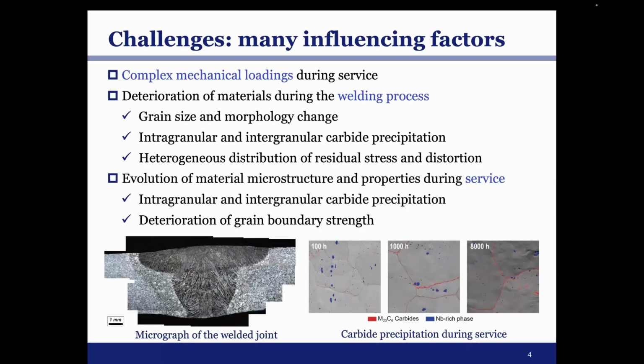For us, it's quite challenging to understand both qualitatively and quantitatively this kind of failure because there are many influencing factors, such as the loading conditions during service, which are quite complex, such as creep and fatigue and their interaction. And also the welding process itself induces some complexity. For example, it creates large grain size and morphology, and also introduces carbide precipitation and also residual stress and distortion. And the material itself during service undergoes changes of microstructure and properties, such as the carbide precipitation at grain boundary, which probably leads to the final failure.